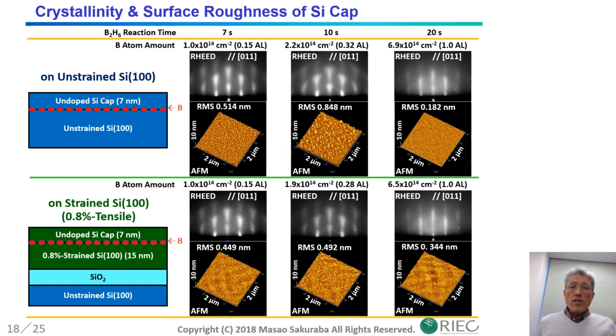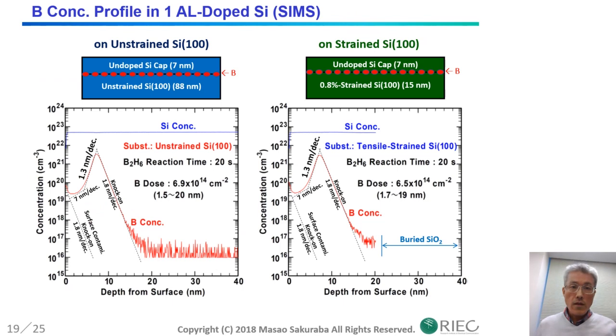By using our low-energy argon plasma CVD, boron atomic layer doped silicon was deposited on silicon without substrate heating. Electron diffraction and AFM analysis show that the films are epitaxially grown and the surface roughness is not so bad. SIMS profiles of boron concentration also show a single boron atomic layer is confined in a very thin region.